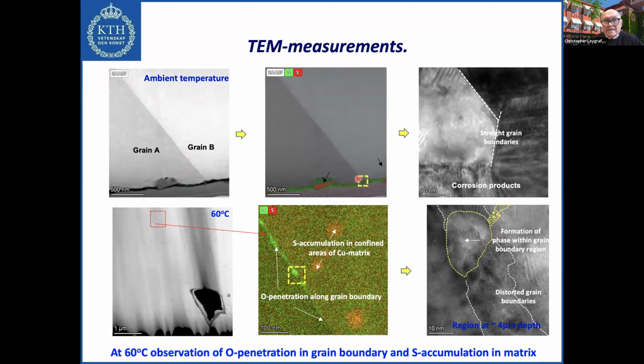And if we select a small area here, this is the X-ray microanalysis for oxygen and sulfur. We just see oxygen and sulfur at the corrosion products. And with TEM, if we magnify this area further, we have the corrosion products here, and we see very straight grain boundaries here, indicating that the microstructure, the grain boundaries don't undergo any particular change in structure. They are really straight lines.